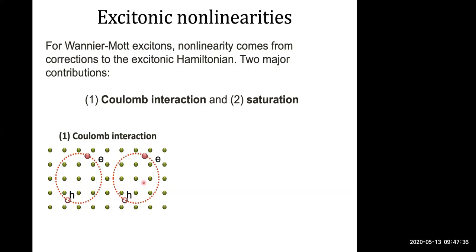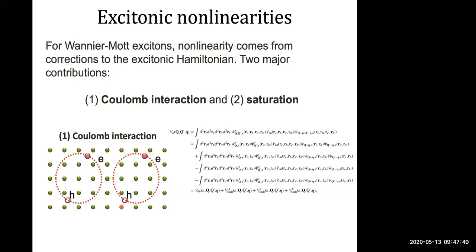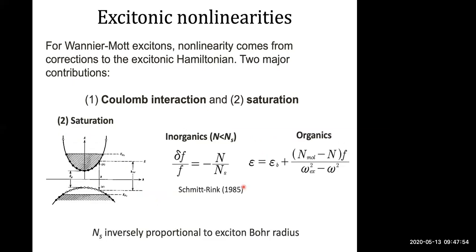And if you have this system with 2 excitons, the total wave function should be antisymmetric with respect to the exchange of 2 of these identical carriers. And this leads to an effective Coulomb term, which is really not present in these organic materials, so we can ignore that. The other contribution is that due to saturation. So in inorganics, you have phase-space filling. So as you increase the density of excitons to a density which is becoming comparable to the inverse of the exciton Bohr radius, you start to have a reduction in the oscillator strength.